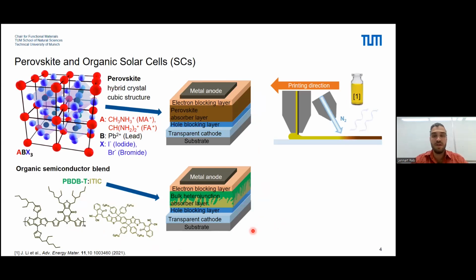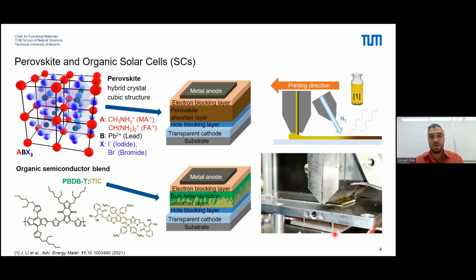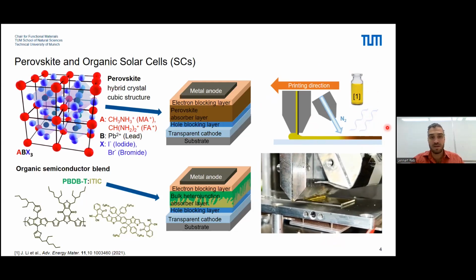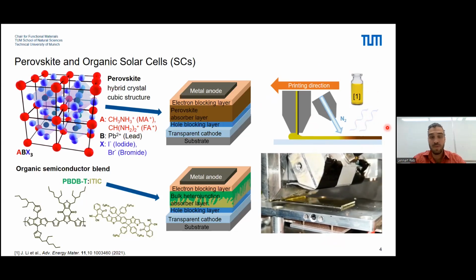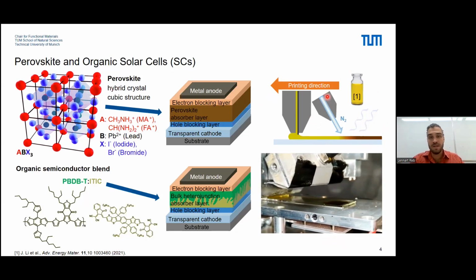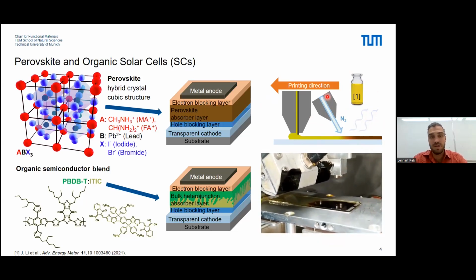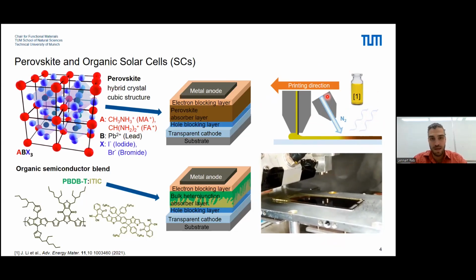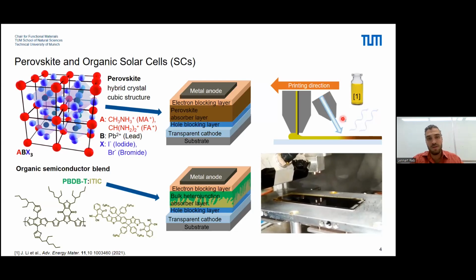What these two materials have in common, and quantum dots also do the same, is that they can be deposited from solution. And this makes it possible to use upscalable solution techniques such as slot die coating. This is printing from an ink. Here you can see a schematic of how this can look, and how it actually looks like in our lab is this here. I'm going to show you a short video about this. So we have the printhead here. The yellow perovskite ink is flowing in the meniscus, and the meniscus is dragged over the substrate, creating a thin, wet film. Then the next step, we have this air knife blowing nitrogen to remove the solvent, to quench it, and to trigger crystallization. And then you can see how it crystallizes by this black optoelectronically active phase. And this film in the end is around 500 nanometers thin and mirror-like, which we want to have.